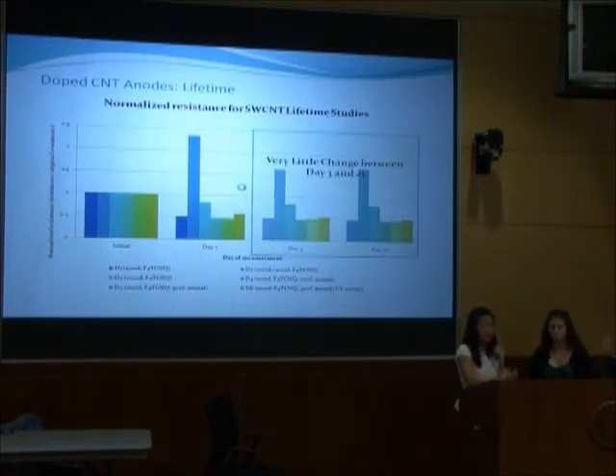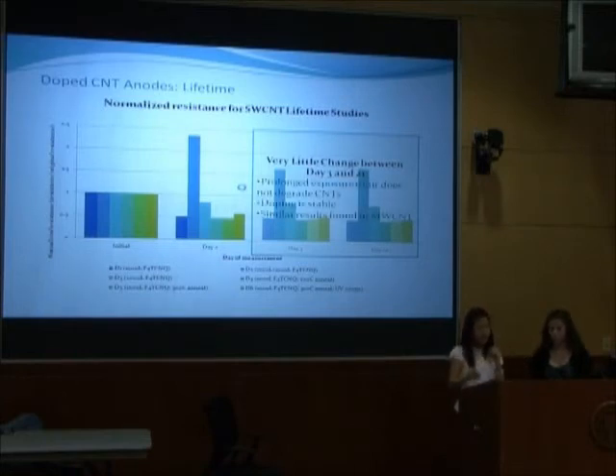Finally, these are the results of our lifetime studies. After we finished doping the nanotubes, we exposed them to air. As you can see, there's very little change between day 3 of exposure to air and day 21 of exposure to air. This showed us that the doping effect is stable, and we also found similar results in the multi-wall nanotubes.